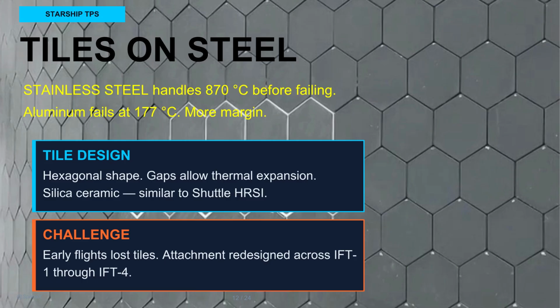Tile attachment uses a fibrous mat interface layer. Tiles are bonded with ceramic adhesive. Replacement requires removing the bonded tile and rebonding a new one. Early test flights showed tile losses. SpaceX redesigned the attachment system iteratively.